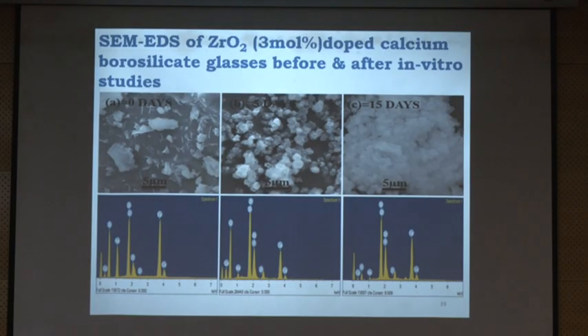Not only that, with SEM also we are able to confirm. See here, this is before immersion, this is 5 days of immersion. You can see the white precipitates on the surface. After 15 days, we can see the cloudy lichen structure. So that is the layer which has deposited on the surface of the material. That is the hydroxyapatite layer which is deposited, which confirms the material is bioactive.